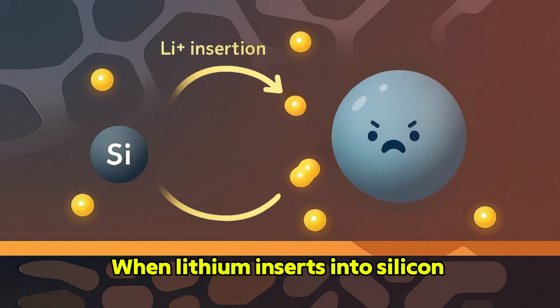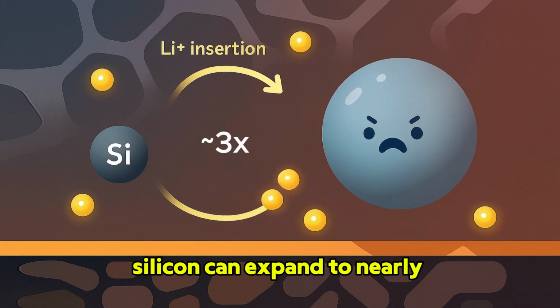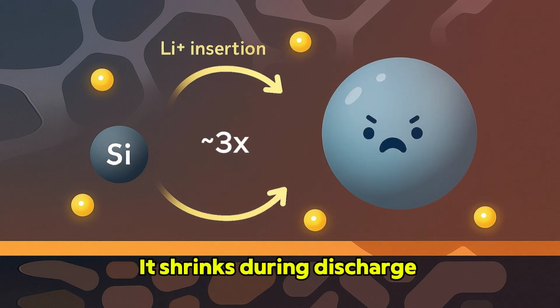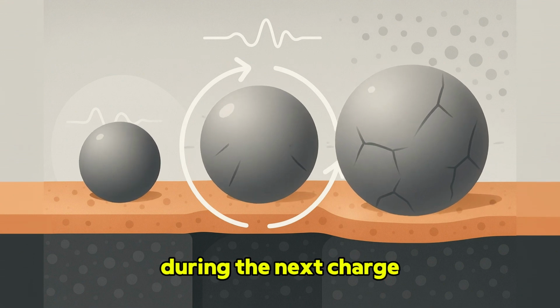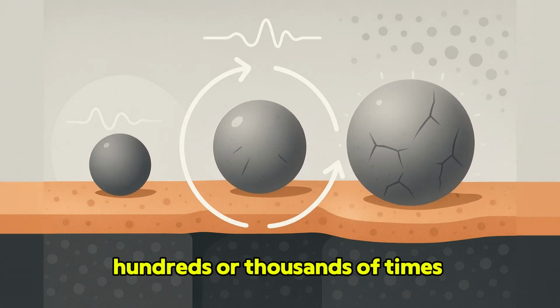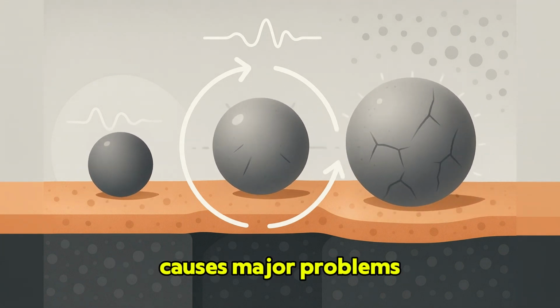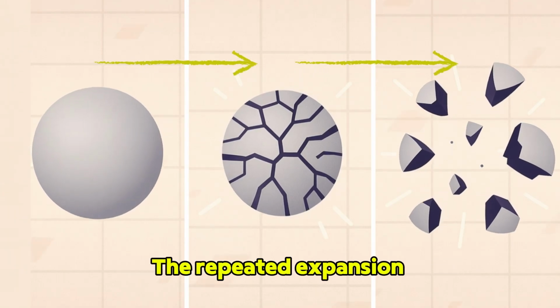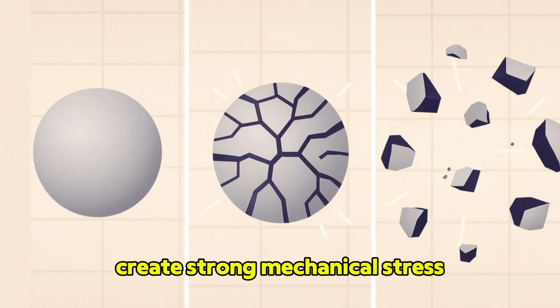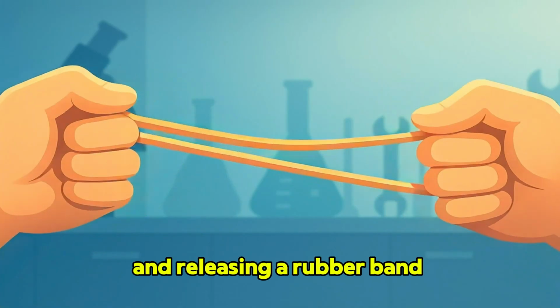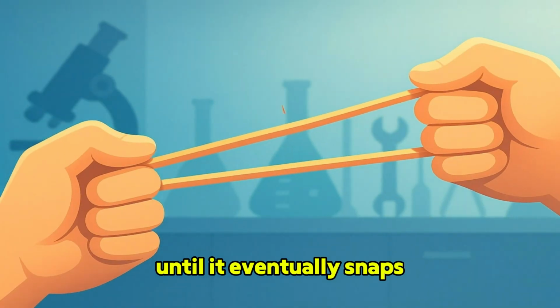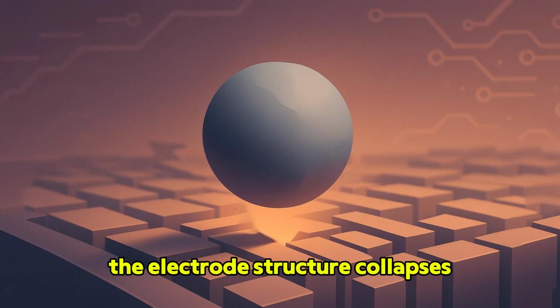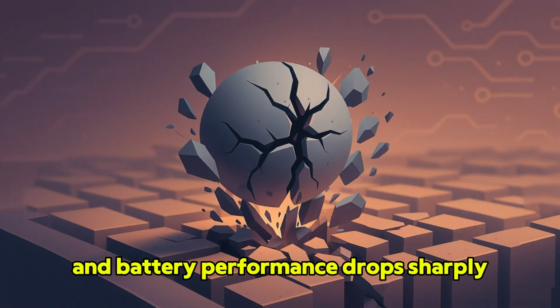The biggest issue is volume expansion. When lithium inserts into silicon during charging, silicon can expand to nearly 3 times its original volume. It shrinks during discharge and expands again during the next charge. Repeating this cycle hundreds or thousands of times causes major problems. The first issue is particle fracture. The repeated expansion and contraction create strong mechanical stress, similar to stretching and releasing a rubber band, until it eventually snaps. When silicon particles crack or break apart, the electrode structure collapses and battery performance drops sharply.